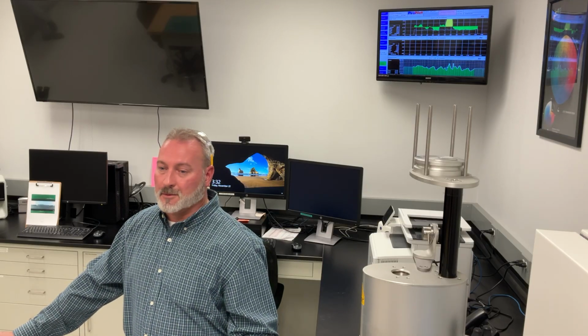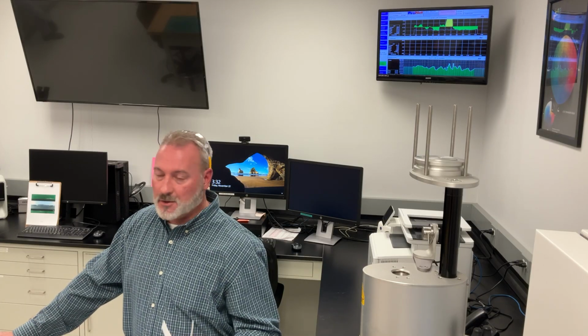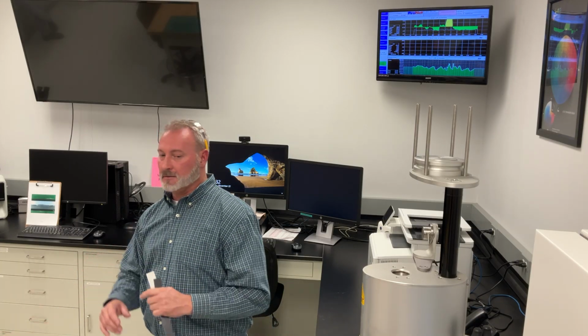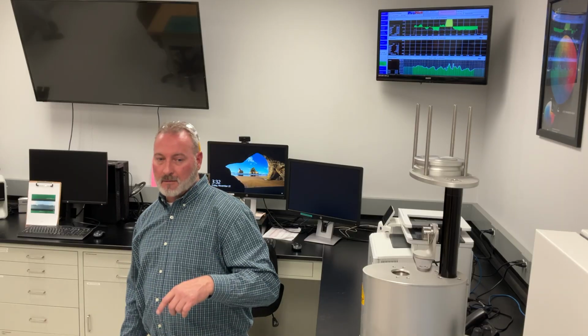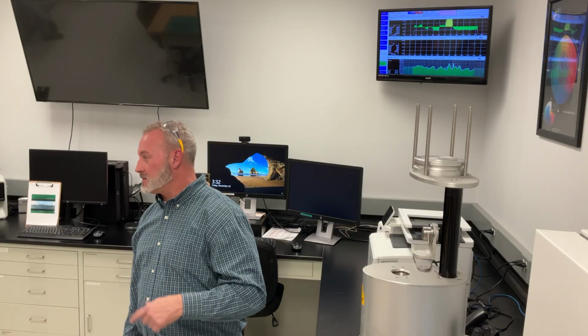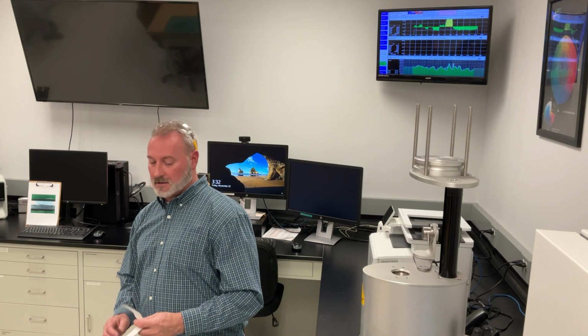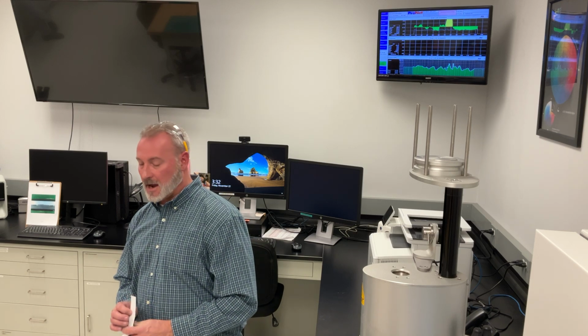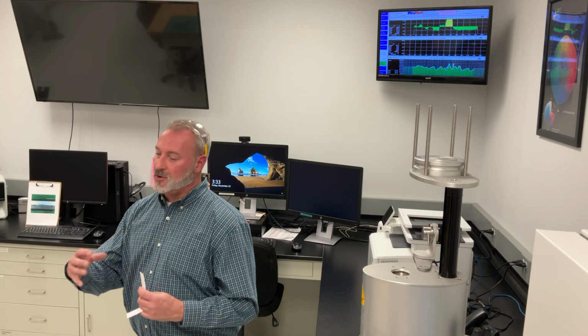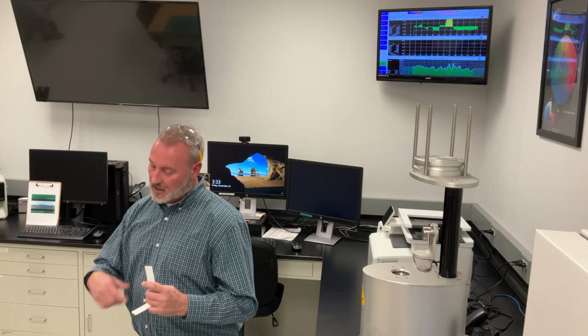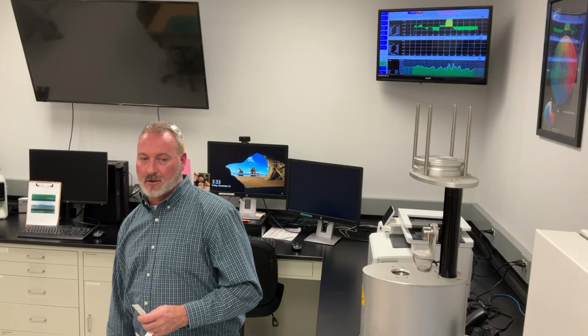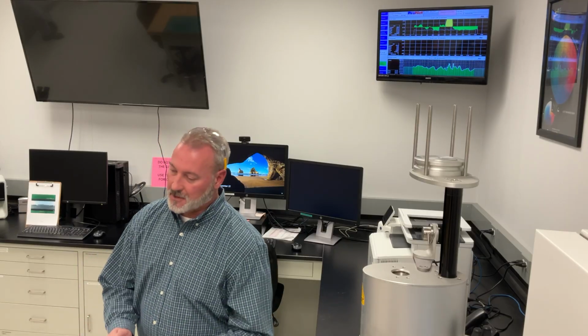We also weather your product. So we have these 2 weatherometers, right? And we load these little 2x3 samples in there. It sits in there for 4,000 hours, right? And it only exposes it to the cap side. So it exposes it to UV and water. And again, it has to run through that cycle. We pull those out, we bend them and make sure that they can't crack, right?